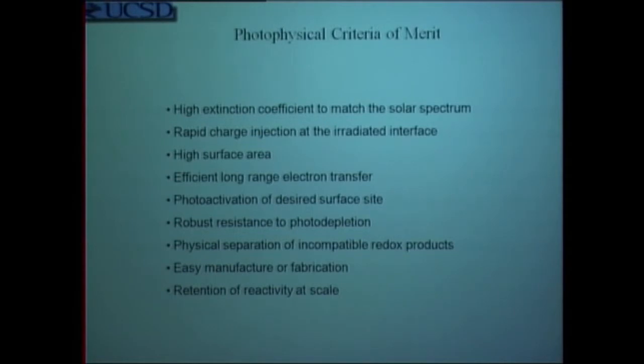So, photoelectrochemistry, in other words, is useful not only because it allows you to do oxidation reduction reactions, it allows you to think of new ways of getting rid of compounds that are of interest, but it also provides criteria of merit that we need to consider. If we're to make this a practical device for doing reactivity such as I described to you, you have to absorb the sunlight very effectively. And titanium dioxide has an absorption maximum of about 410 nanometers if undoped. And because it's not doped, it won't absorb a large fraction of the visible spectrum. So you have to figure out a material that can be used or added as a dopant or a surface-bound reagent that will allow you to bring photons to the site where chemical reactivity can take place.